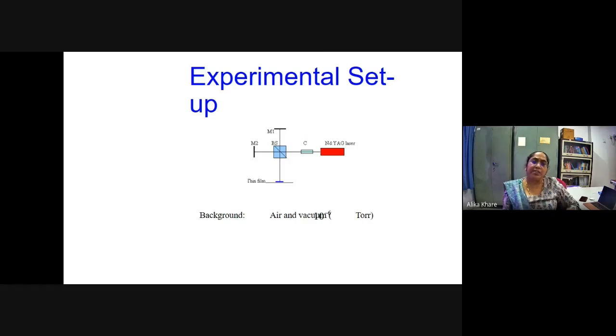The experimental setup is very simple. One can have the thin film, made from any kind of system, whether pulse laser deposition or any other system. And we have the Michelson interferometer. The laser has to be high power so that the material can be ablated, so we use the Nd:YAG laser. Collimation probably is not required because the Nd:YAG laser itself is quite a high power laser with a fairly big beam, 7 to 8 mm in size. So normally collimation and expansion are not required.